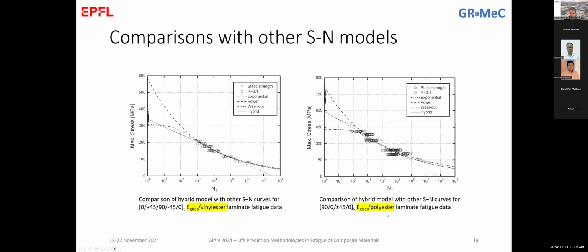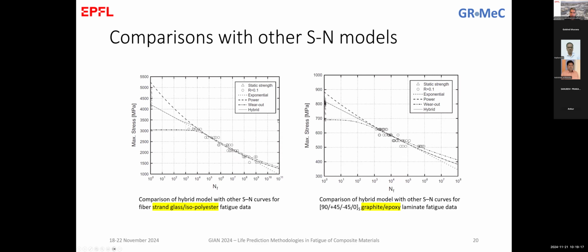The same happens in another material. Here is glass vinyl ester and glass polyester material, data that we got from different sources. Again, the power law goes very high. The linear model goes low at the high cycle fatigue. Our model is in between and fits better the fatigue performance of materials over the entire lifetime.